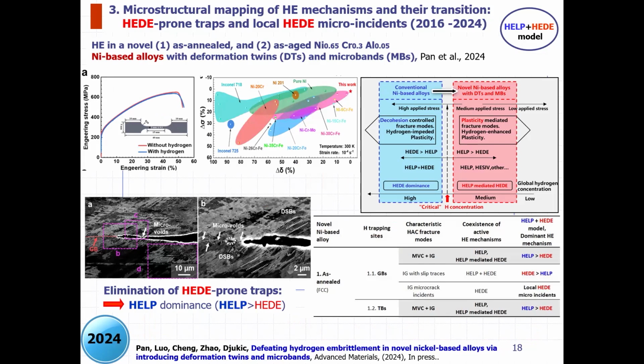Here is, again, work with a group from China and Serbia. As you can see, we provide a very high resistance of nickel-based alloy. Nickel-based alloys are typically very prone to hydrogen embrittlement. We provide the explanation based on the HELP HEDE unified model of what is happening in this material. But what is very interesting is that we introduce deformation twins and microbands into the microstructure of the novel nickel-based alloy, which, as you can see, provides a combination of decohesion and microplasticity. Microplasticity means that we have remaining ductility of our material.